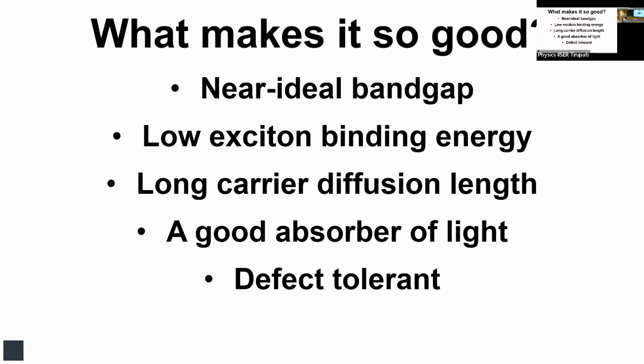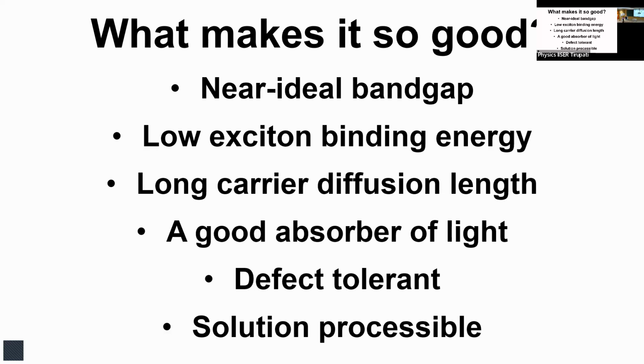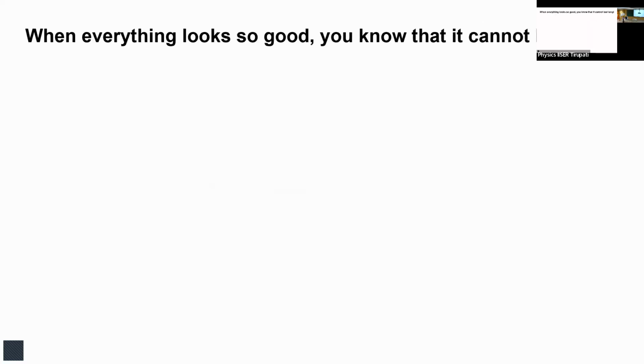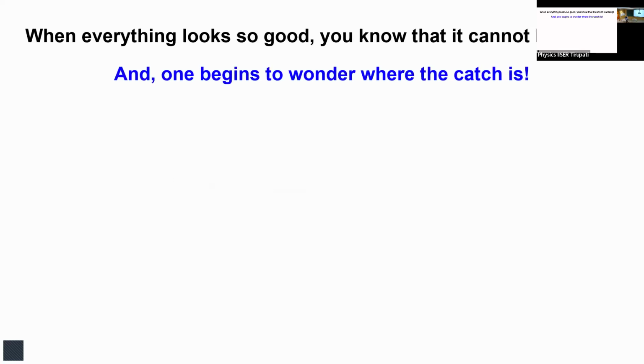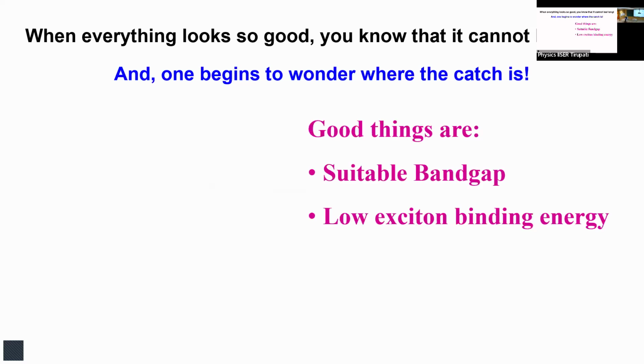So everything sounds so good that one begins to wonder, and I've already said it's soluble, that there must be something not quite right. When everything is going good all the time, getting the maximum score in all the quizzes one after the other, you know that the end sem will have some surprise. And this particular compound has very bad news in the end sem. When the end sem came, people figured out where the catch is. It was fantastic, with a suitable band gap, low exciton binding energy and all that, but environmental stability.